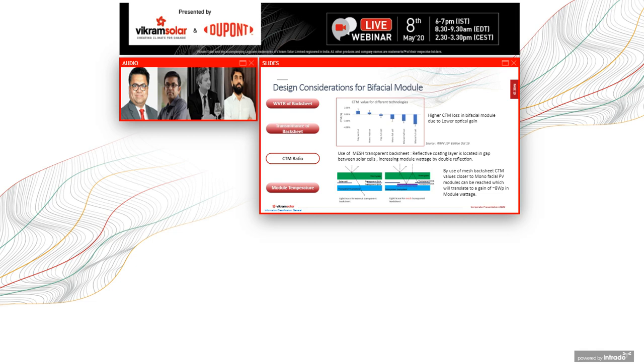module ratio, conversion ratio. Because the material is transparent from the front and the back, some of the light is going to pass through, and you are not going to capture that light because in between the gaps of the cells, there is about 1.5 mm gap between the cells. The light that goes through those gaps, you're not going to catch. And therefore, the CTM, cell to module loss, is significantly higher in the case of bifacial modules.